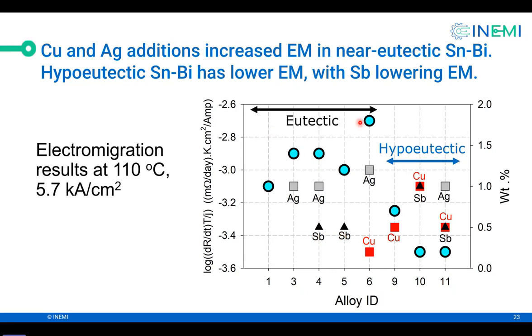That's for eutectic solders. Now, before I forget, there's a fifth one, which is alloy ID6. The electromigration rate has gone up very high because the silver addition is also high. I forgot to mention the right side is the weight percent alloying element. Here the silver is 1.2%, and there's some copper there. So maybe there's synergy between silver and copper. The rate of electromigration has gone much higher because of silver and maybe also copper. So that's eutectic or near eutectic cases.